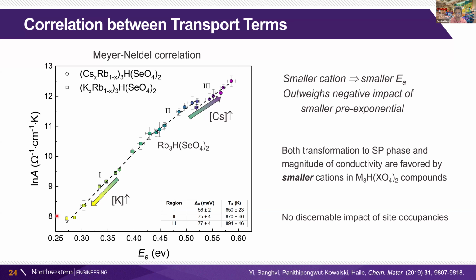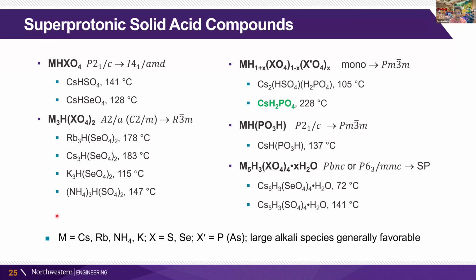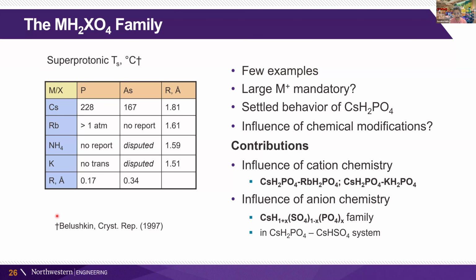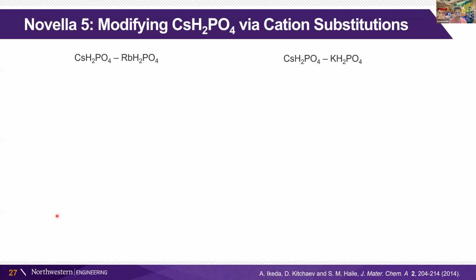So we have a smaller activation energy when we have a smaller cation, and that gives us ultimately the higher conductivity, even though the pre-exponential term is lower when we have more potassium. All right, so let me go back now to the cesium dihydrogen phosphate system and look at this family overall. As I said, we wanted to look at the influence of replacing some of the cesium with rubidium or some of the cesium with potassium, sort of motivated, as you might expect, by this behavior in the selenate compounds. And there's a lot of disputes here about what's true and what isn't true, so we'll just leave that as that.